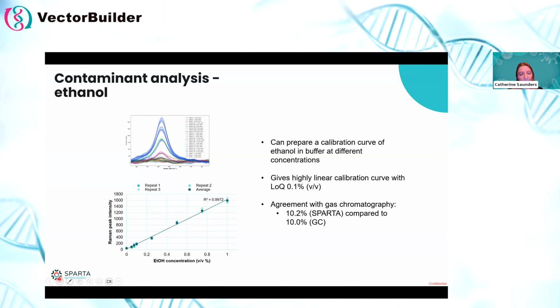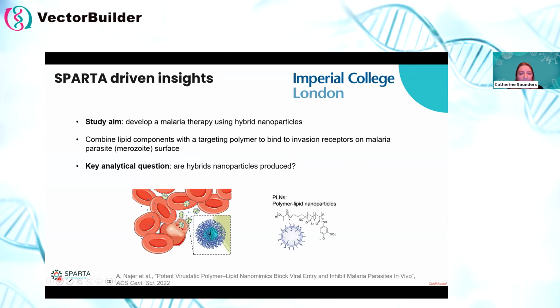And now, of course, the proof is in comparing to real samples and established techniques. And in this, we also get very excellent agreement. So you'll forgive me, this is ongoing work, so I can only share one number with you at the moment. But using this method and correcting for sample dilution, we calculated a SPARTA ethanol concentration of 10.2%, which is within 2% error of the gas chromatography measured value of 10%. So that's been a little snippet of what SPARTA is able to show you beyond what you're, let's say, expecting in your sample.